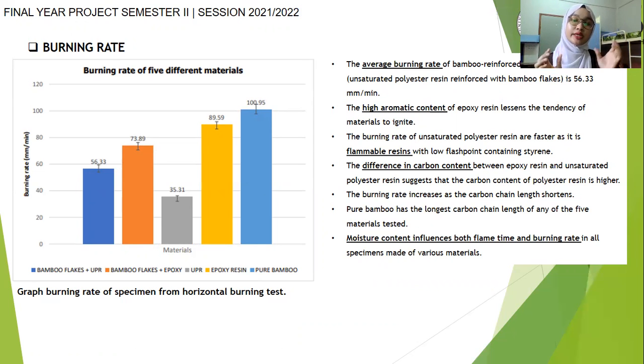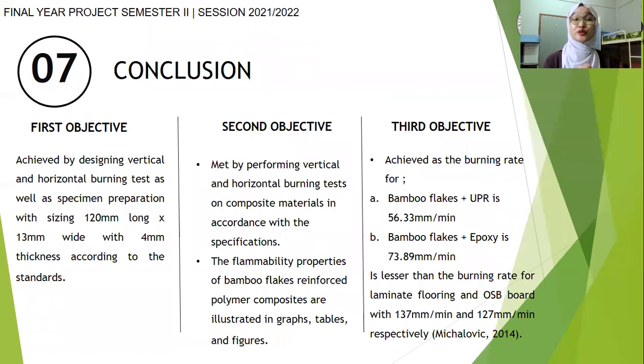carbon content between the epoxy and UPR itself is what results in the burning rate, because the burning rate increases as the carbon chain length shortens. Therefore, pure bamboo, which has the longest carbon chain length of the 5 materials, has the highest burning rate, and moisture content also influences both the flame time and the burning rate of all specimens. Move on to the conclusion.